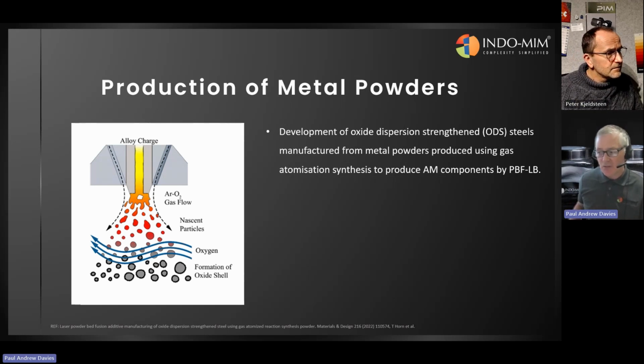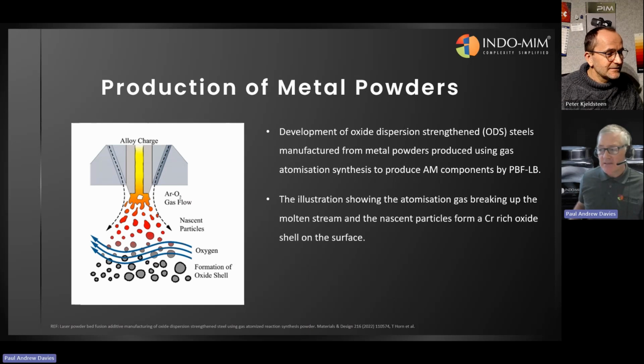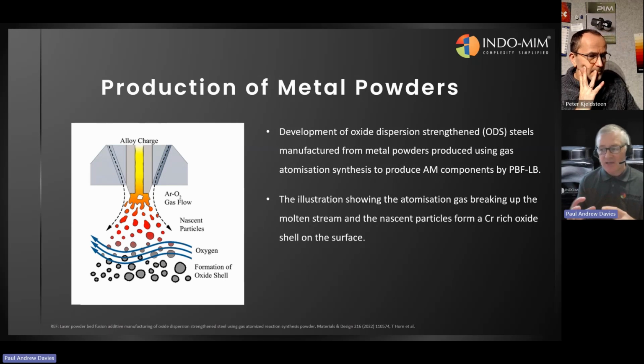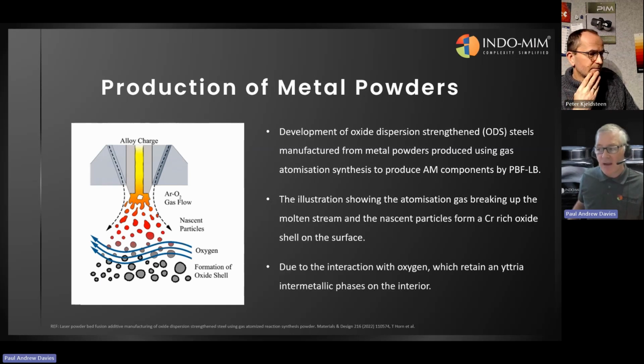However, there's a number of researchers in North America from universities and Ames Laboratory, for instance, who started using atomization process and introducing oxygen, rather, into the atomizing gas, and what that does, it reacts with the chrome to form a nice chrome-rich oxide on the surface, and then the oxides which react with yttria are trapped inside the particles. So it provides a nice pool of oxides for manufacturing by additive manufacturing.